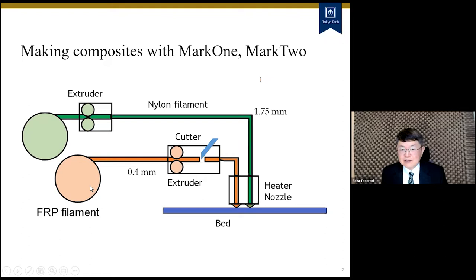And the other nozzle is used to print the continuous fiber composite. This filament is a composite, not the fiber. This filament is composite, and the diameter is 0.4 millimeters. And of course, as this is continuous carbon fibers or continuous glass fibers, to make a short specimen, we have to cut the fibers. So the fiber cutter system is installed here.